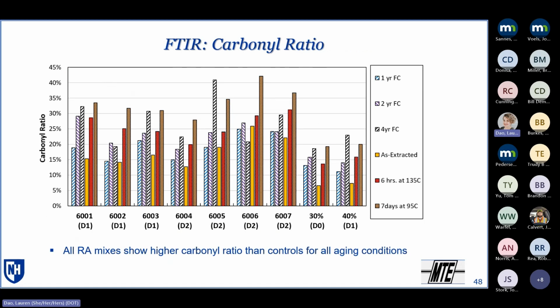Now getting into some of the other tests, the FTIR. Looking just at the carbonyl ratio in this particular figure, all of the RA mixes, regardless of the aging condition, have a higher carbonyl ratio than the controls, and that's with the different additives. It was not unexpected to see this, but you can see that it is happening. And again, as you expect, as we're seeing the aging, these are increasing a little bit.